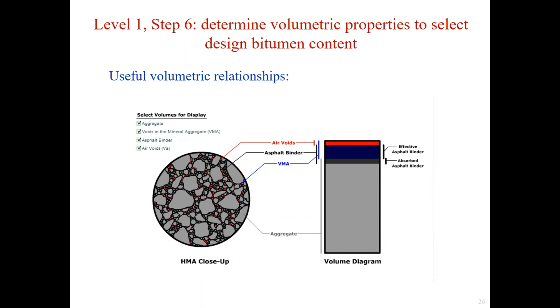In the diagram, HMA stands for hot mix asphalt. The bigger particles are the aggregate. Some of the asphalt is absorbed into the aggregate. The VMA, or voids in the mineral aggregate, are occupied by the air voids and effective asphalt binder. From the volume diagram, we can also see that the asphalt binder is composed of the effective asphalt binder and absorbed asphalt binder.